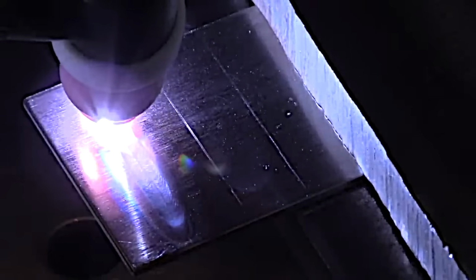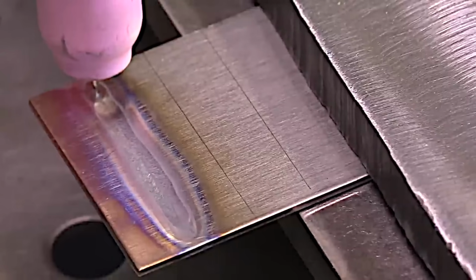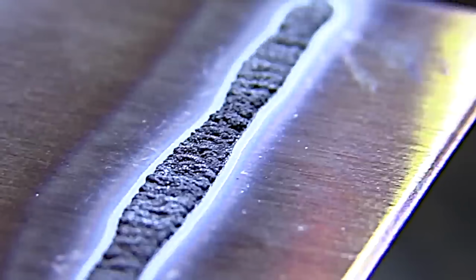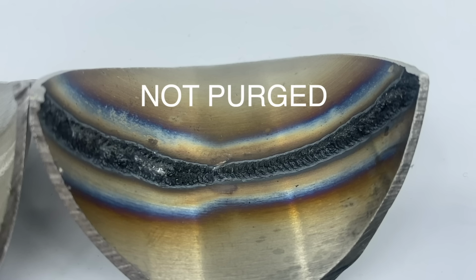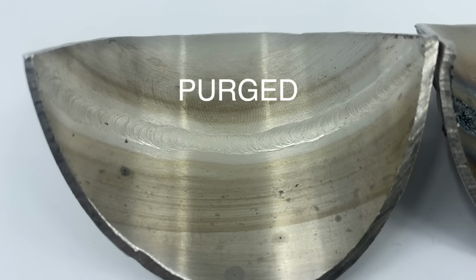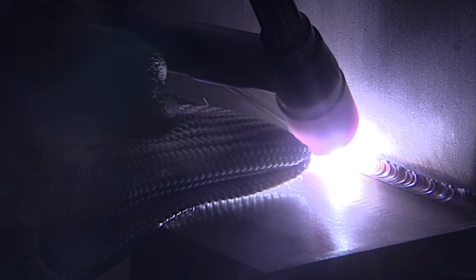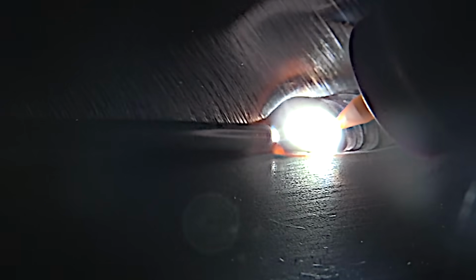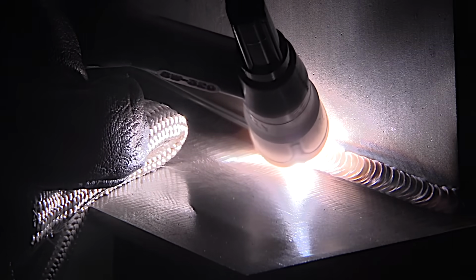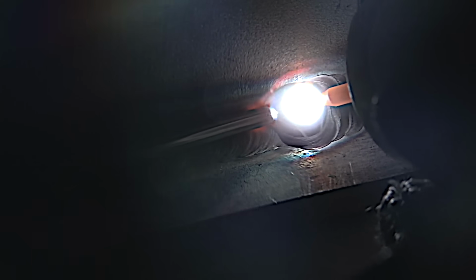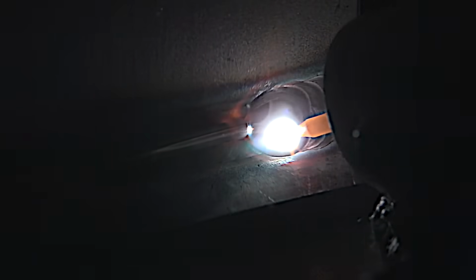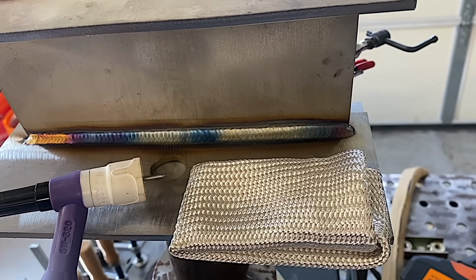Let me show you a really good example of just welding full penetration with no argon or no backing or anything on the backside. That's an area where bacteria can grow, and in some jobs it's an area where a crack can start. There's an example of not purged, no argon gas, as compared to purged. Night and day. Stay tuned for a future episode of the Weldmonger podcast where we're going to dive in more deep to stainless steel, metallurgy of stainless steel, things like carbide precipitation, what is it, what causes it, how to avoid it, with plenty of practical application.